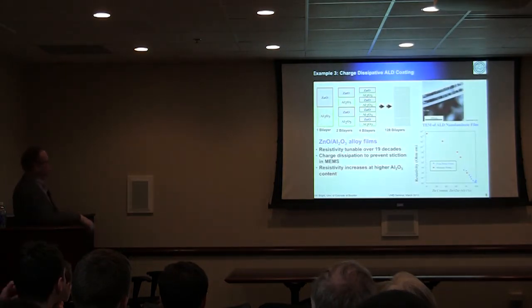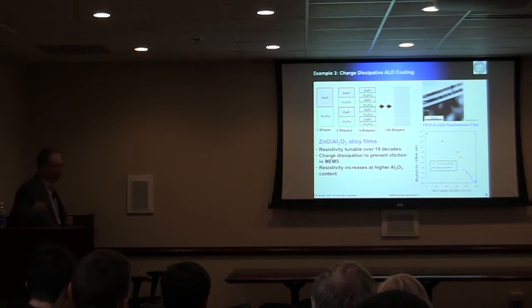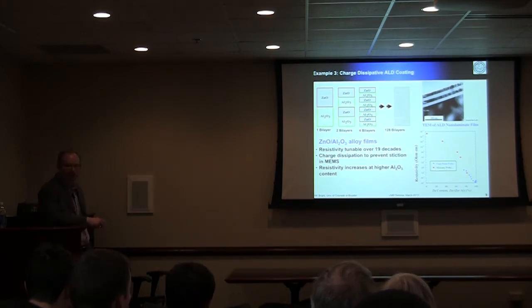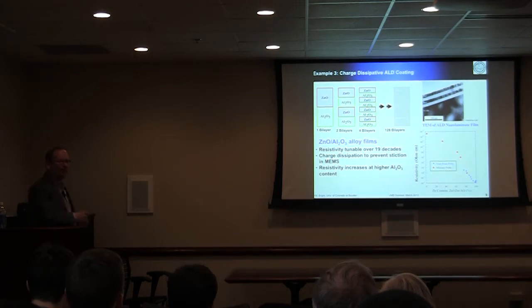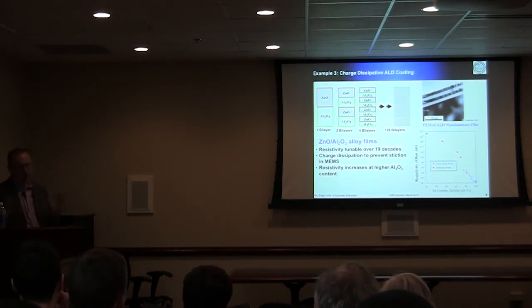But what's interesting is when you combine zinc oxide and aluminum oxide. You can make a superlattice. This is all done in the same reactor, actually. You can grow this kind of structure. You can do a coating layer of alumina, zinc oxide, alumina, zinc oxide, and so on. Depending on the thickness of individual layers and overall composition, you can control resistivity or conductivity depending on how much zinc you have in a composite. And it's very interesting because this one here is tunable over 19 orders of magnitude of the conductivity. So you can make a coating that bleeds out the electrical charges, which would be an interesting application.